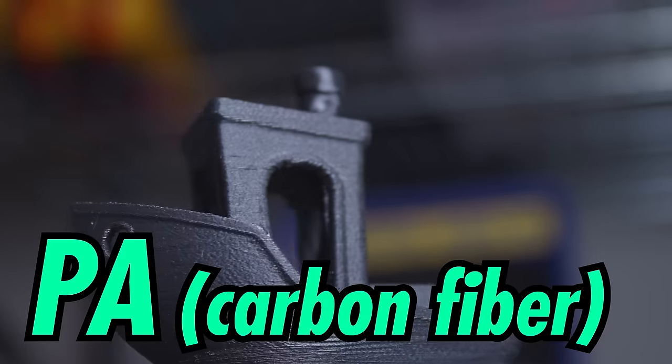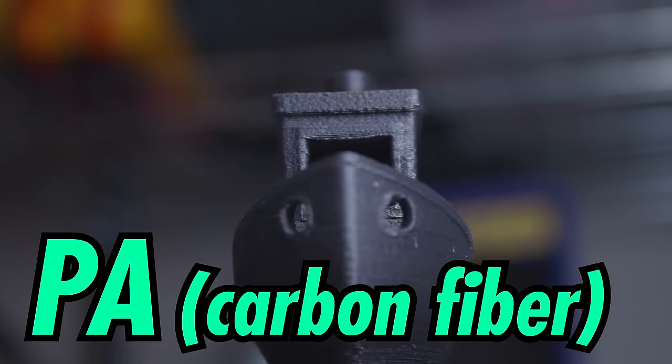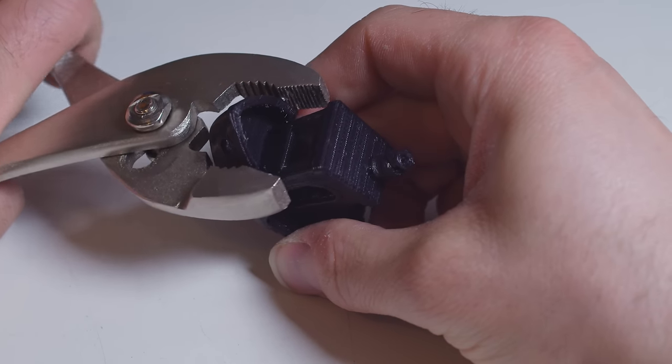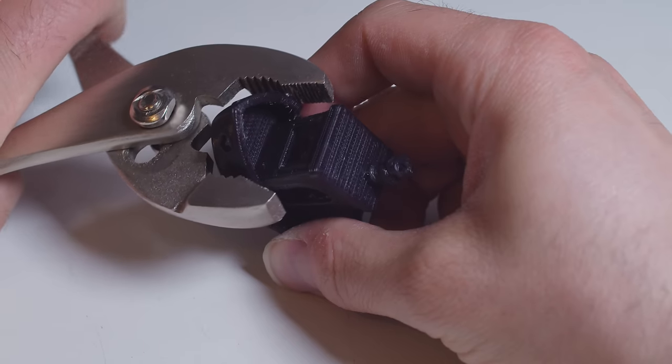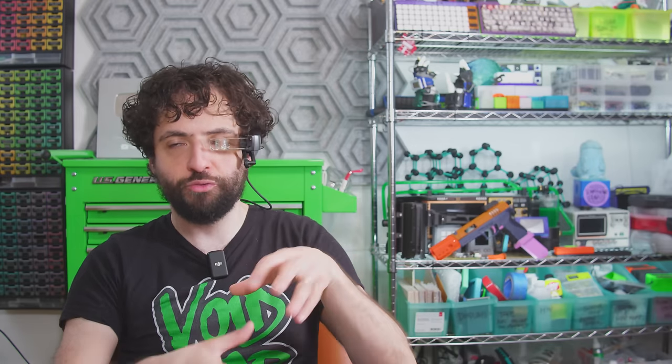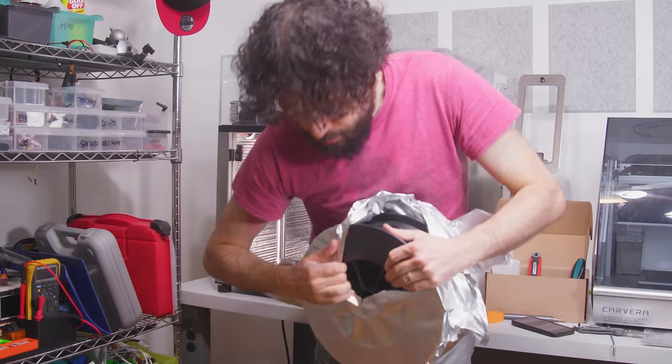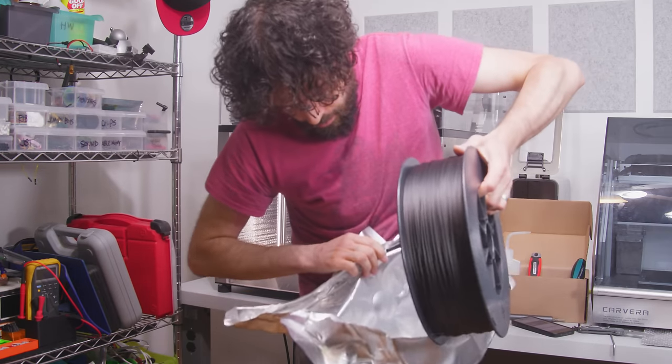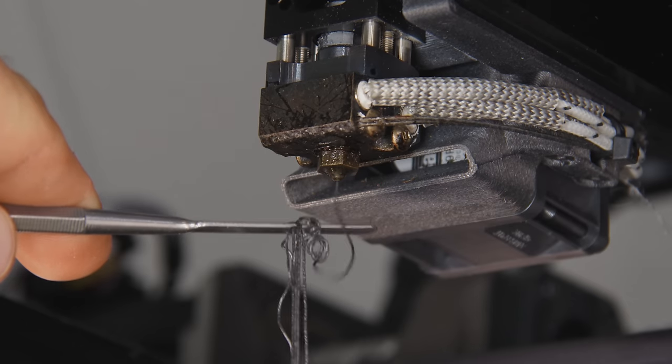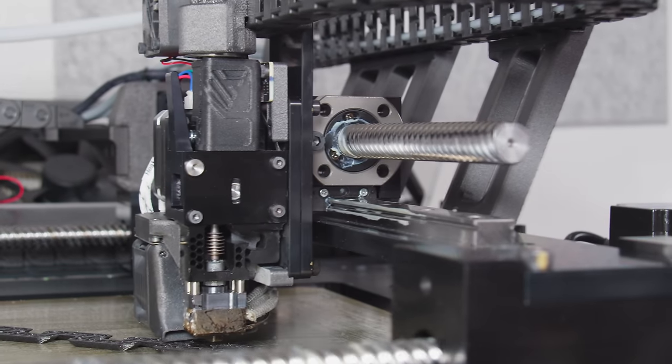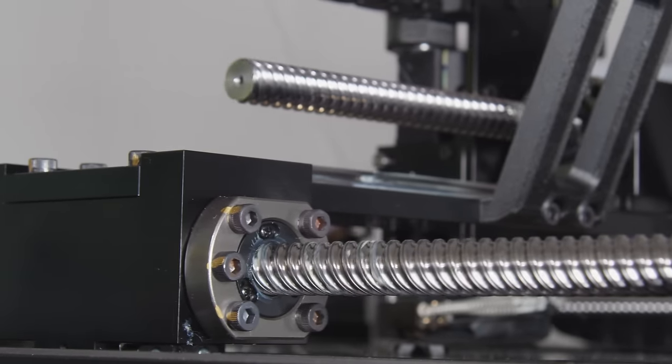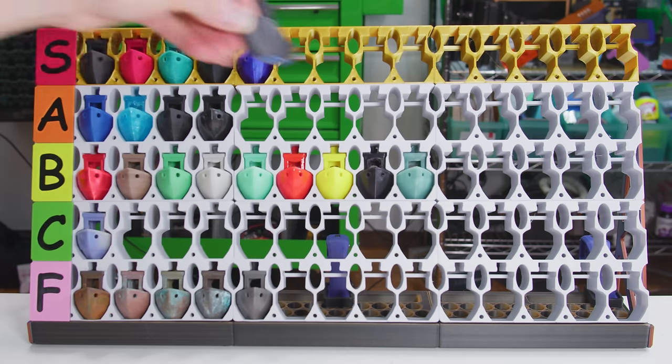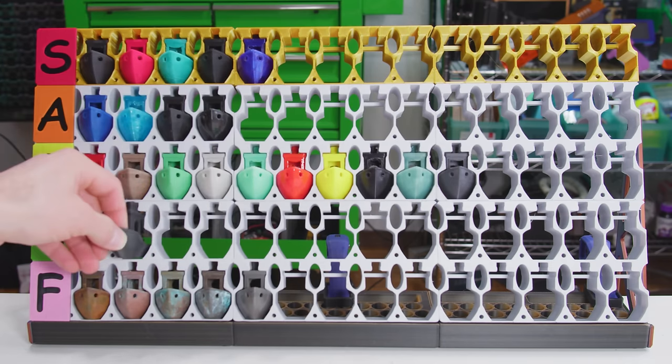Carbon fiber can seriously improve nylon's performance. But unless you're using a real fancy pants printer, the difference just is not there. Carbon fiber nylon, usually called PACF, is stiffer than vanilla and warps a lot less. But even 80% less warping is a shitload of warping. You also sacrifice nylon's low friction, and you need an insanely powerful hotend to preserve those high-powered layer bonds. This Pantheon HS3 is so overbuilt specifically because it's meant to print CF nylon at high speed. You need a powerful drive motor to force the filament in, fire-breathing hotend to get it out, and a powerful gantry just to whip all that around. I'm gonna put PA6 CF in B tier and PA12 CF in C tier.